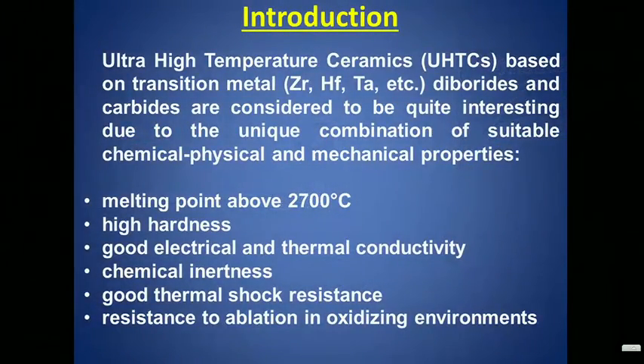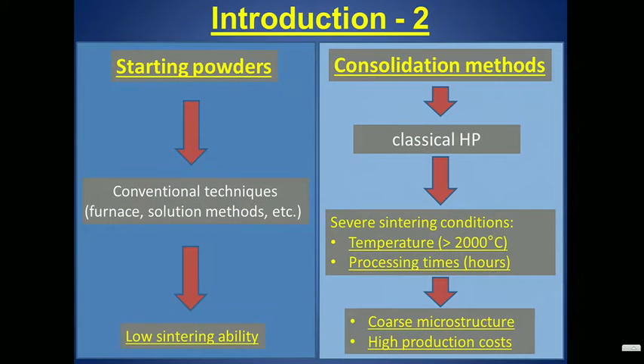You might know that these materials are considered to be very interesting for their unique properties. These properties are a high melting point, good thermal shock resistance, and particularly resistance to ablation in oxidizing environments. If you take a look at the production of these materials, what you see in the literature is that conventional techniques for producing starting powders give rise to low sintering ability. If you look at the consolidation techniques to sinter the starting powders, for example hot pressing, you get very severe sintering conditions, and typically a coarse microstructure and high production costs.